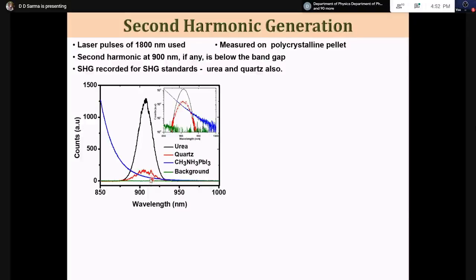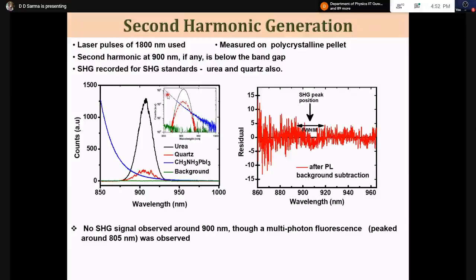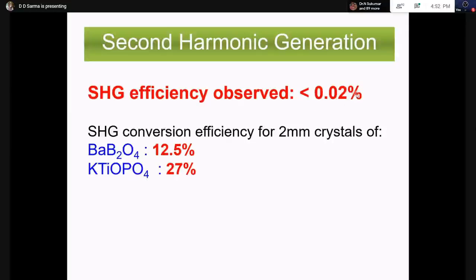In order to inspect whether there is a peak here or not, I'm plotting this whole thing in log scale shown over here. And you can see it's a smooth line going through. There's no sign of a peak here. I can fit a smooth line and subtract it out to look for the peak more closely. After subtracting a smooth line from here, this is the signal that you get. If there were a second harmonic peak, it would be positioned here, and its FWHM would be that much. That I know from my test samples of urea and quartz. And you can see there is absolutely no second harmonic generation within the noise level, such that we can put an upper limit on the second harmonic generation activity, which is less than 0.02%, whereas standards have 27%.